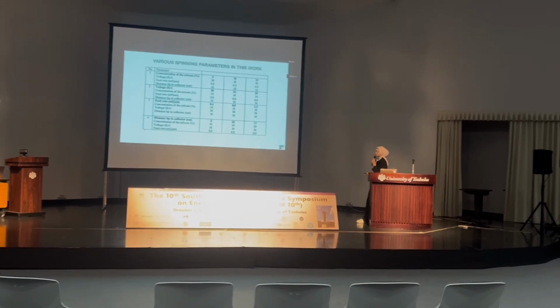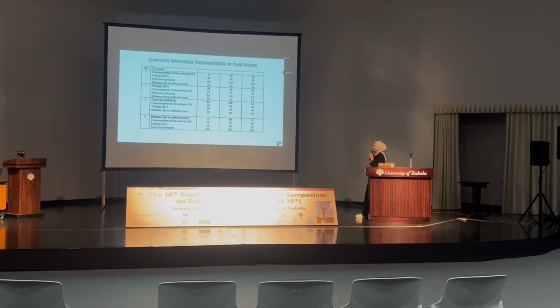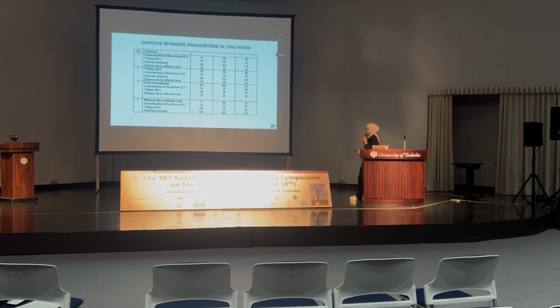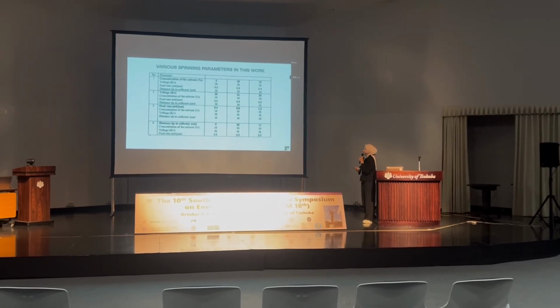And finally, I prepared the fourth sample where the distance between the tip of the needle and collector was adjusted from 5 to 10 to 15 centimeters. By using the scanning electron microscope, the diameter of the nanofiber was investigated.